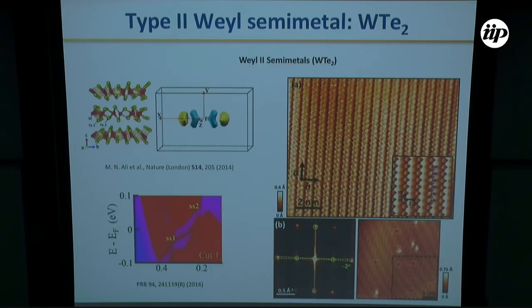So we have made a QPI study of this material. This is a topographic image that we obtained after cleaving the sample with the method that I showed you before. We can directly see these atomic chains that are expected from the crystalline structure. When we do larger scale imaging, we can also observe defects on the surface, which can be seen in the bottom image. Essentially, we find two types of defects, one which are missing atoms, which are holes, and others which are like adatoms. So we have seen the effect of both types of defects.